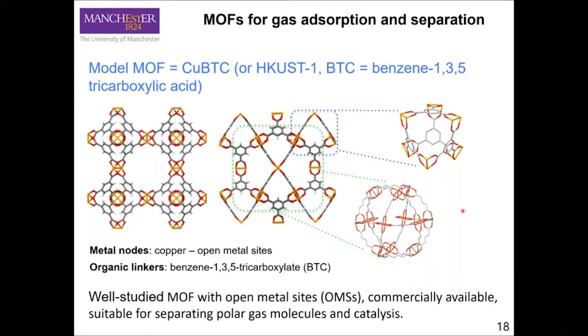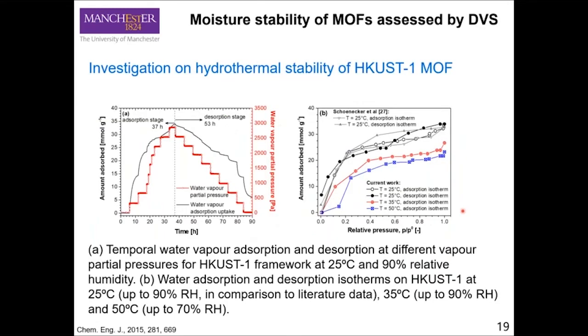Initially, I had a student working on these materials for gas adsorption, mainly for CO2. We tried to simulate the adsorption of CO2 from flue gas, where CO2 is quite dilute, only roughly 10%, and there is a lot of water vapor involved. Therefore, we wanted to study the water vapor stability. And this is when we used the DVS system to measure the water adsorption behavior of this MOF.